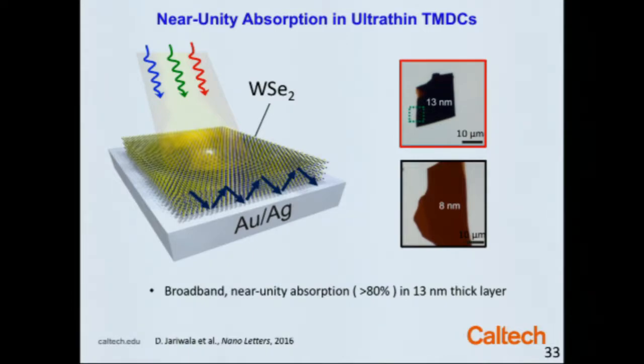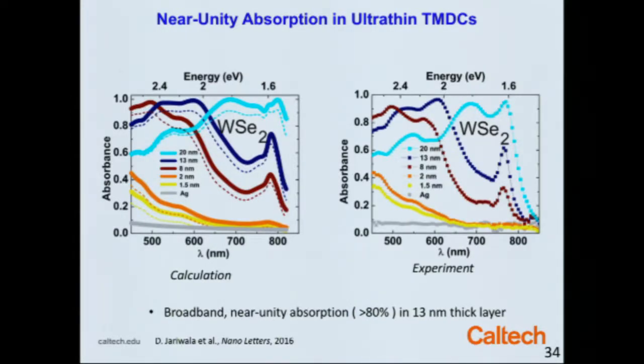And it's not. What we're seeing is actually a resonant interference condition that is built up at special thicknesses, where we can get very high absorption, and we can see broadband absorption, more than 80% in layers that are less than about 20 nanometers thick. This is some transfer matrix calculations showing absorption as a function of thickness, from 1.5 nanometers up to 20 nanometers, and these are the experimental results. You can see we get pretty close to bulk absorption when we get above about 15 nanometers.